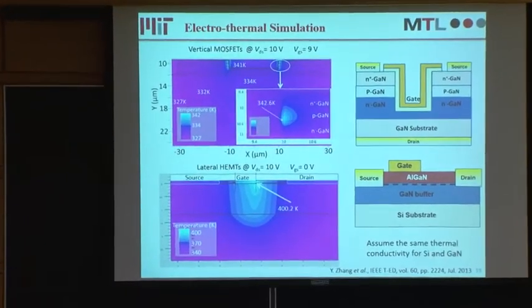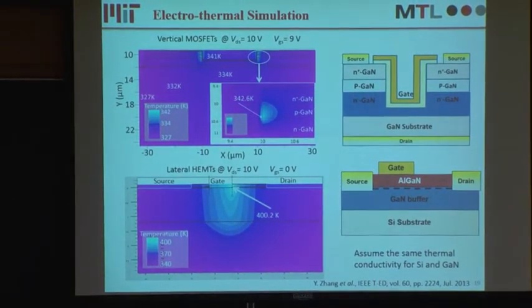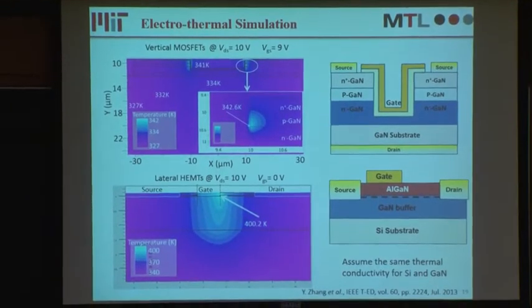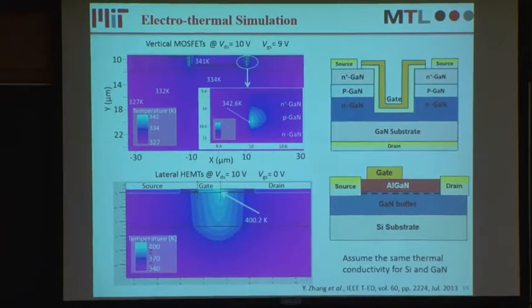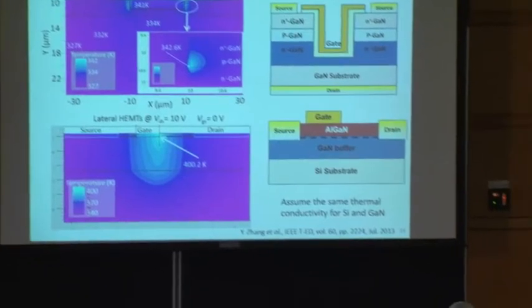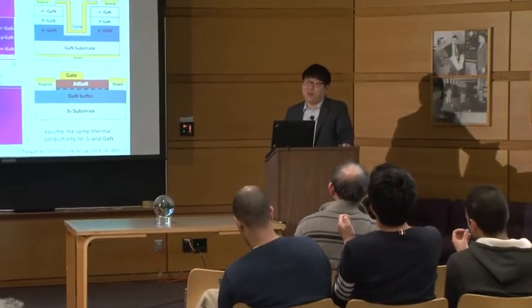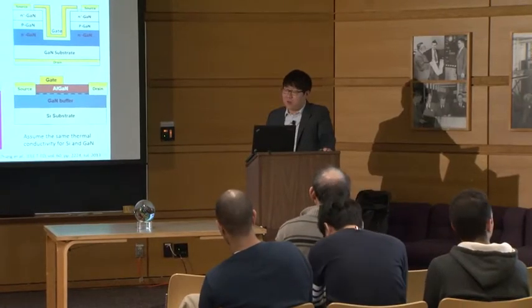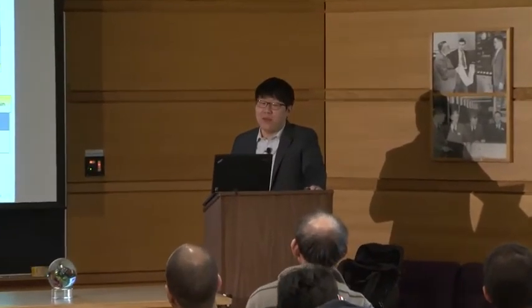For the first question, this electrothermal simulation is 2D, done 3 to 4 years ago. But I think in the future we need 3D simulation, especially for multi-finger devices - it's very important. At that time, we calibrated with experimental results mainly through IV curves, considering all thermal effects. We also built a thermal reflectance system in our lab to accurately measure temperature distribution in real devices, and we're still improving this experimental setup. In the future we need to also calibrate the simulated peak temperature with experimentally measured temperature.